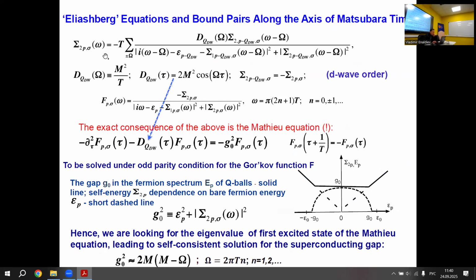So let us now see what the Gorkov-Green's function looks like. So this is the energy, the correction to the denominator of the Gorkov-Green's function, and this is actually an Eliashberg equation. So what we see here is the self-energy of the fermions in the anomalous Gorkov's function. This is D. This is correlation function of the M field. And this is actually Eliashberg equation. What is the difference with the usual Eliashberg equation? That we do not have here summation over Q, because Q is a single wave vector of the deformation in the Q ball. And all the rest is as usual.